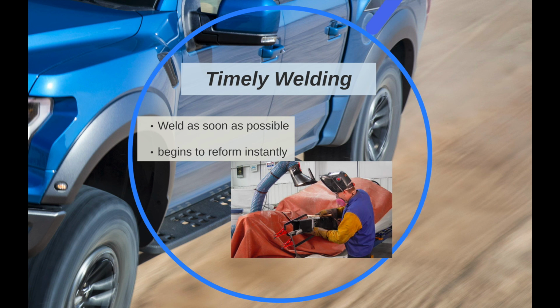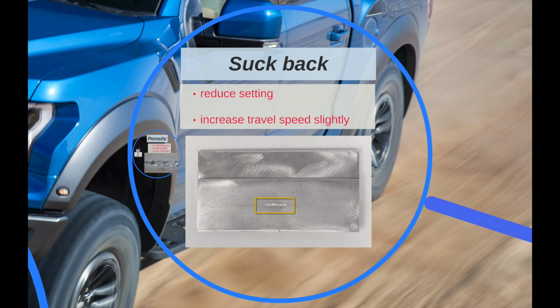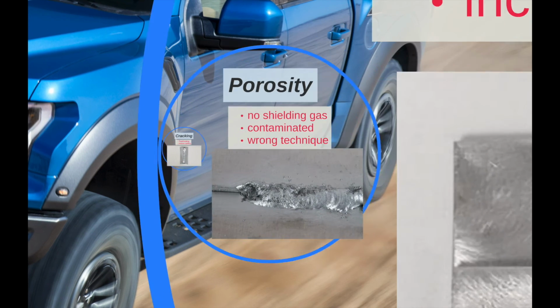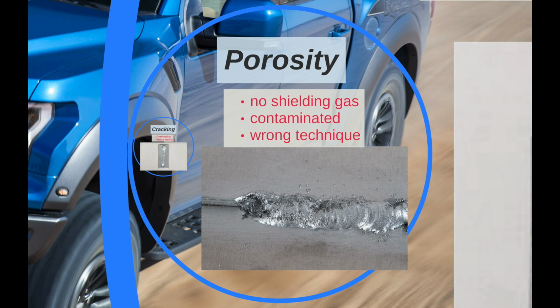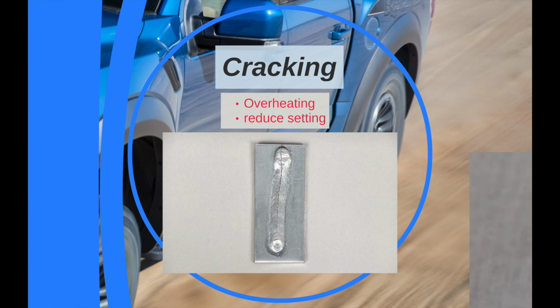Other than that, I want to mention some common mistakes that happen in welding. Suckback. It means too much heat. We could reduce the setting and increase travel speed slightly. Porosity. It happens because there is no shielding gas or something is contaminated. Maybe the shielding gas, electrode wire, or the welding piece wasn't cleaned properly. Last thing is cracking. It is always caused by overheating. We could reduce heat to solve this problem.